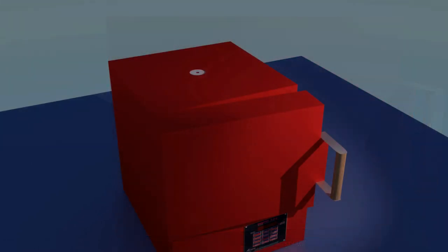Set your oven temperature for 1350 degrees Fahrenheit. That is about 730 degrees Celsius. Typical burn out time is about 1 to 2 hours. When the smoke stops, the process is done, but leave the oven on for about 1 half hour just to make sure.